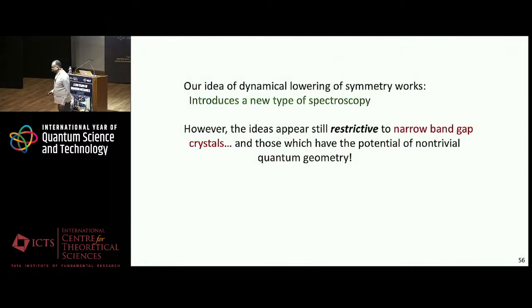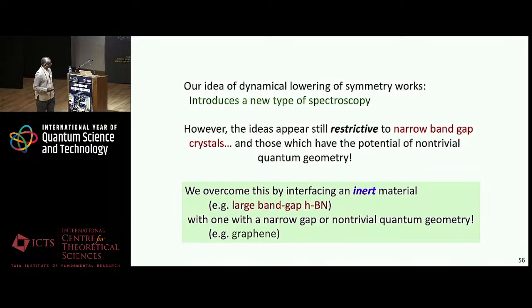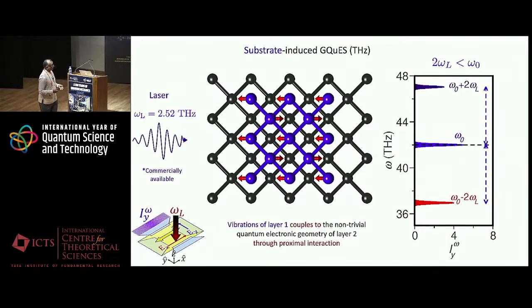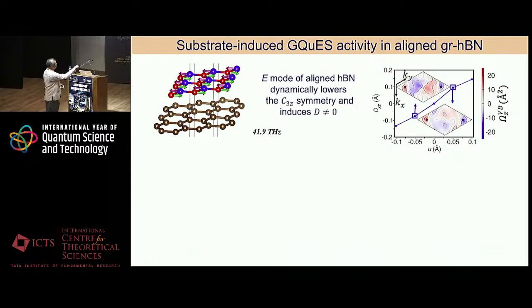At this stage, some of you will be quite critical. This is applicable only to materials with non-trivial quantum geometry, and there are not too many materials with such properties. Well, we overcome this limitation by learning from surface enhanced Raman scattering, where we use a substrate of a quantum geometrically active material like graphene that Mandar talked about, and then measure frequencies of something like boron nitride. Boron nitride is a boring insulator which has a large band gap and no non-trivial Berry curvature.